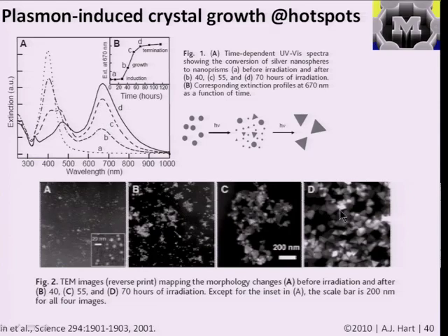And it's not completely clear what's going on here, but certain energies and certain wavelengths of light are effectively reducing the silver, or causing a light-mediated reduction reaction in solution, which my interpretation is, in combination with the fact that you have a higher concentration at the tips of these particles, causes them to grow into these triangular prisms.